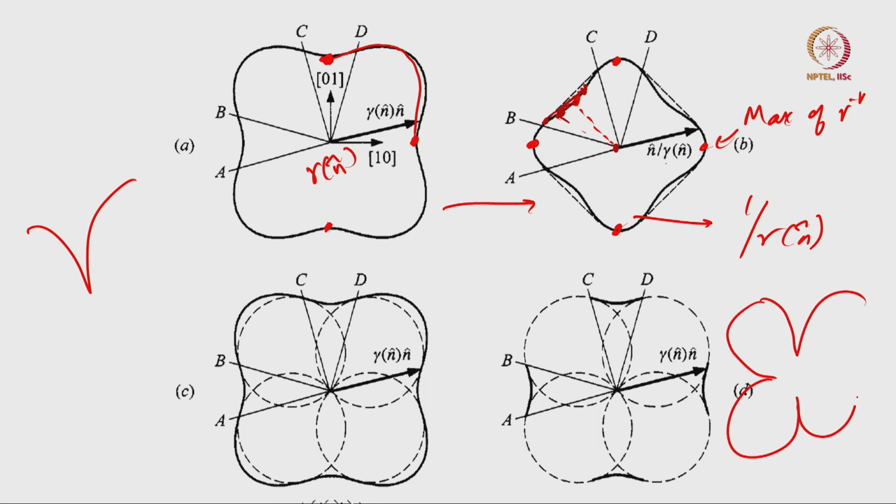So very simply put, if I am drawing a circle from the center, a circle that passes through the center and is tangential, of course the maximum tangential I can be is wherever these 2 points are hitting, right. So especially with such large singularities, everything outside of this singularity is an unstable surface. Any of these surfaces is going to split into this surface and this surface. Okay. So that's how I can understand why I have faceting in crystals.